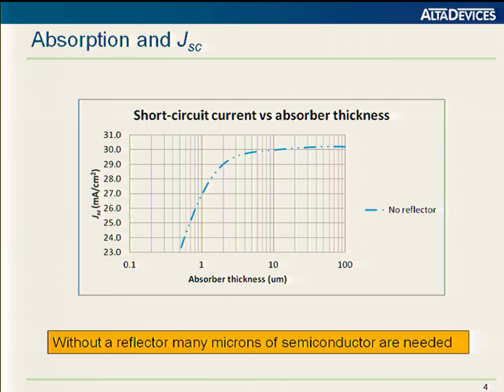The point of this slide is that to achieve industry standard values close to 30 milliamps per square centimeter for gallium arsenide, you really need close to 10 microns, or maybe that's an exaggeration, but at least many microns of material to achieve these kind of JSCs.